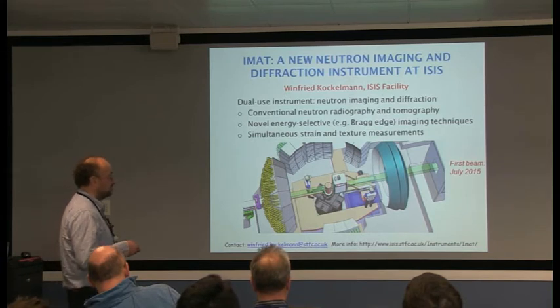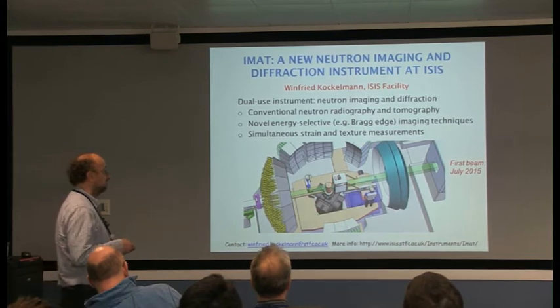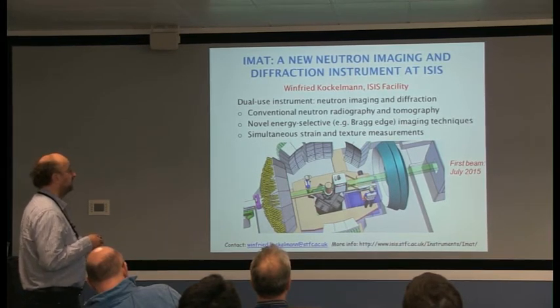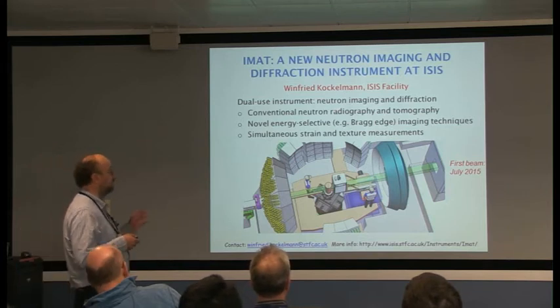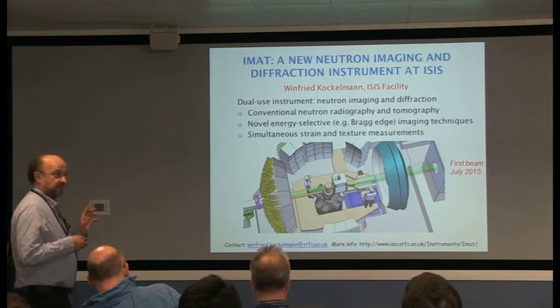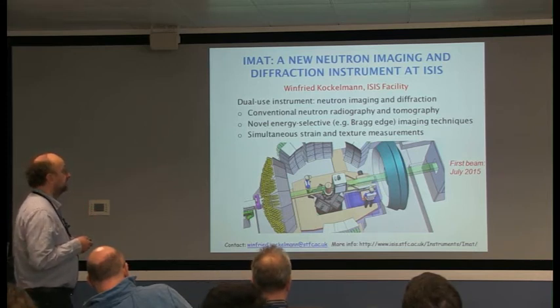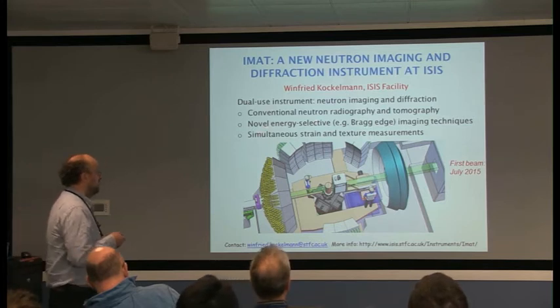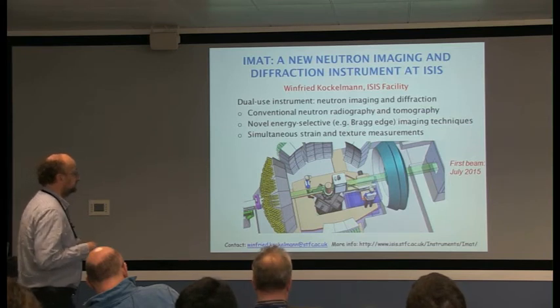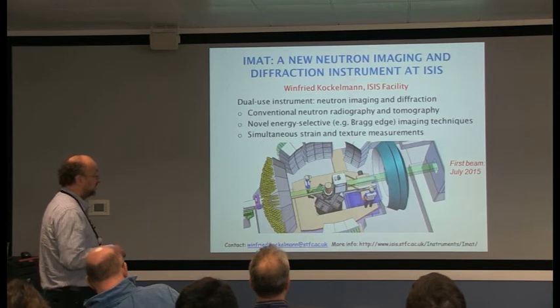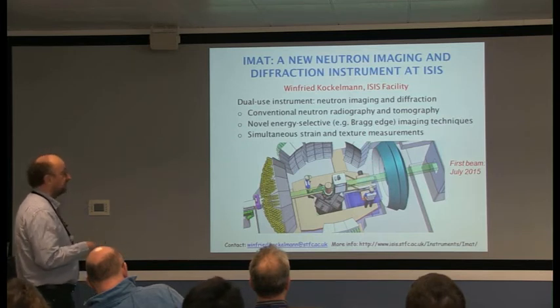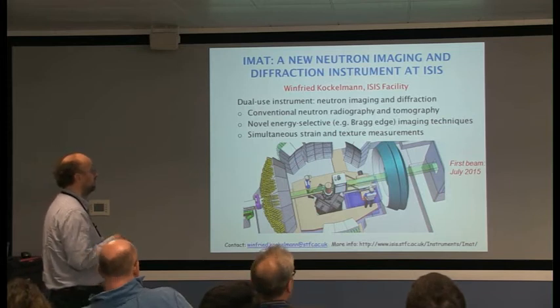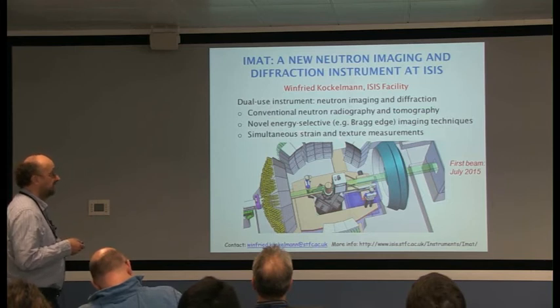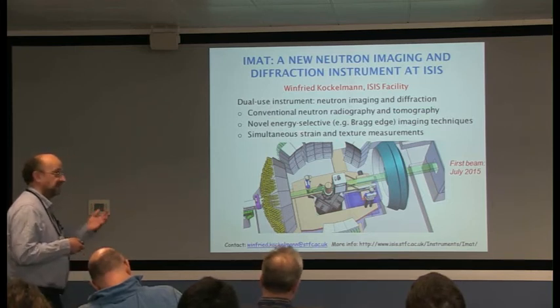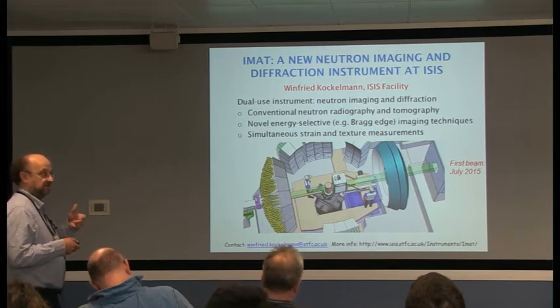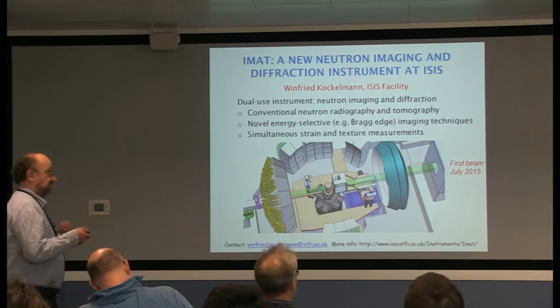We have a sample. We will have a choice of neutron imaging cameras. And what we want to do is conventional neutron radiography and tomography. But we also want to exploit the specialities of our source, and that's the pulsed source and time-of-flight diffraction. So we have some options for some new energy-selective imaging techniques. And then, not next year, but eventually we will build up large arrays of diffraction detectors, and we'll use those to do bulk strain and texture measurements, and do that also simultaneously. And typically, like on ENGIN-X and also on IMAT, we will do in situ measurements.